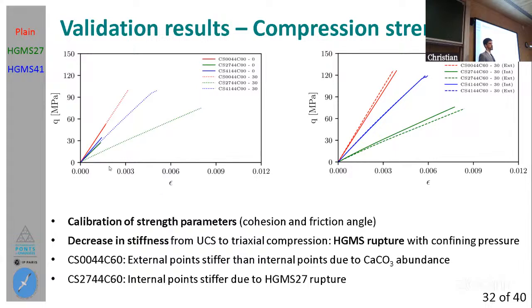First, in this first figure you have in solid line the results of the non-carbonated cement specimens on the unconfined compressive strength. Then the dotted lines correspond to the same non-carbonated cement paste, but with a confining pressure of 30 megapascals. Here we have an increase in the deviatoric pressure, of course, but then what we see is that we have the same stiffness regardless of the confining pressure for this plain cement paste, the red one. If we go to the other extreme, the HGMS27 cement paste, we see an increased strength of the material, but a decrease in the stiffness.